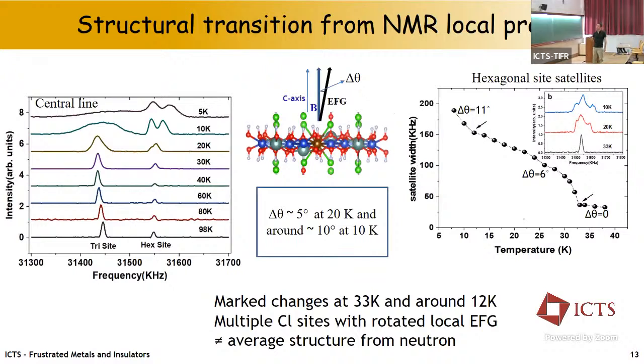Okay. So now when we lower the temperature below 40 Kelvin, in between 40 Kelvin and 30 Kelvin, the line moves as the susceptibility, and then the line shape changes. So first, both on the triangular site and the hexagonal site, whether the central line or the satellite, we do see some changes. For instance, if I look at the hexagonal site here, it broadens and even splits into different lines, or at least two. And so we can follow it also on the satellite. Here is the evolution of the satellite, and that's the width of the satellite. There's a clear change at 33 Kelvin at the structural transition, and there's a subsequent change here at 12 or 13 Kelvin, which is where there was a peak that you didn't see on the thermal expansion.